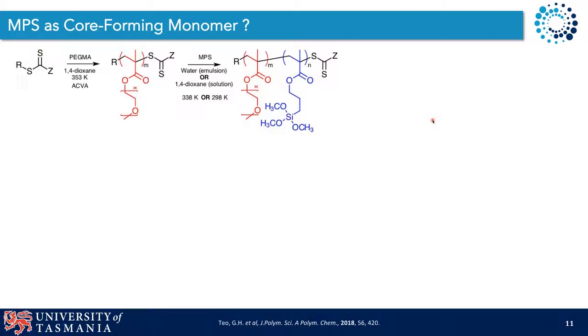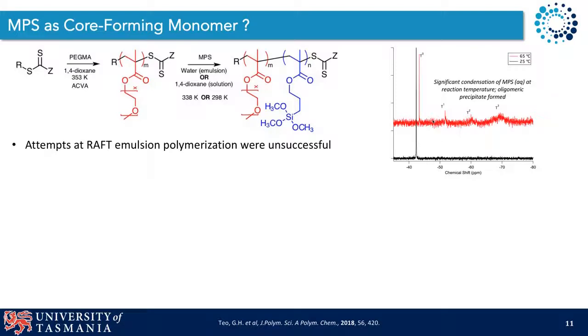We also wanted to try the idea of switching things around and using MPS as a core forming block in a RAFT emulsion polymerization system. This, however, was unsuccessful. We were not able to use this monomer easily under aqueous conditions due to significant condensation of the monomer at the reaction temperature, as emphasised by silicon NMR studies.